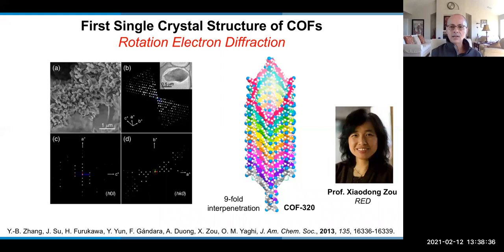This was very exciting because now we can get to the atomic arrangement with great definitiveness. Now we can determine that indeed this material is 9-fold interpenetrated and not 8 and not 7, because from X-ray powder diffraction, sometimes it's not easy to decipher the level of interpenetration. So this is one of the early powers of this electron diffraction technique in characterizing COFs.